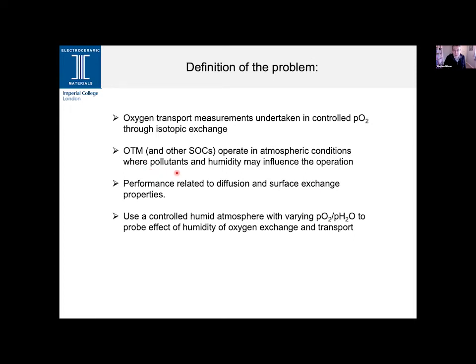And so the device itself clearly, its performance is related to some of those key kinetic parameters. So the oxygen diffusion through the material, but also those surface exchange reactions, including that oxygen reduction and charge transfer across the surface. So to tackle that problem, what we've looked at doing is using a controlled humid atmosphere, varying the partial pressures of oxygen and steam to probe that effect of humidity on those oxygen exchange and transport properties.